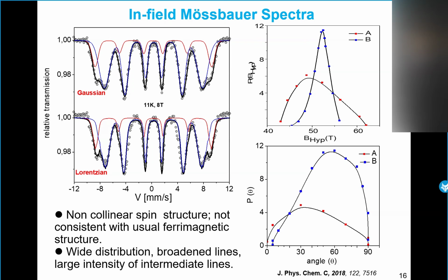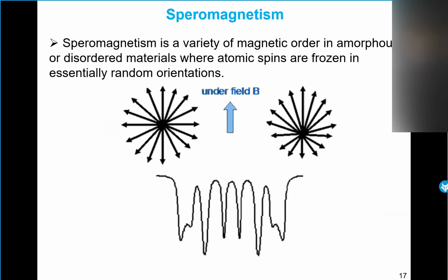The most important information here is the large, broad distribution of the spin canting. It covers all the space from 0 to 90 degrees. That means we have spins in all the directions. So from this fit, it's okay, we arrive to fit the spectrum. But the shape of this spectrum is not so different from the theoretical spectrum under field of the speromagnetic behavior. Speromagnetism, as presented by Jean-Marc, is an exotic magnetic order observed usually in amorphous or disordered materials, where the atomic spins are frozen in random orientations. So each spin has a specific magnetic orientation. But we have some difference in the external lines here and here relative to our experimental spectrum.